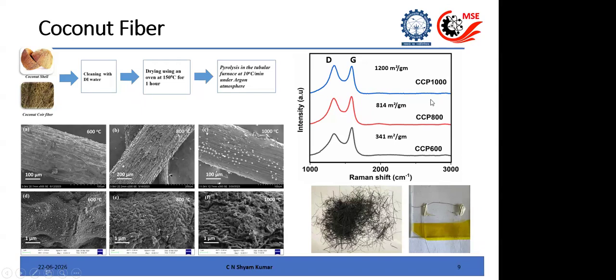And these are Raman spectroscopy, which we use to measure the graphitic content. What this shows is that as you increase the temperature, the graphitic content is increasing from 600 to 1000. And when you look at the SEM images, you can see the porosity is also evolving. So at 1000, you have a moderately graphitic porous carbon.